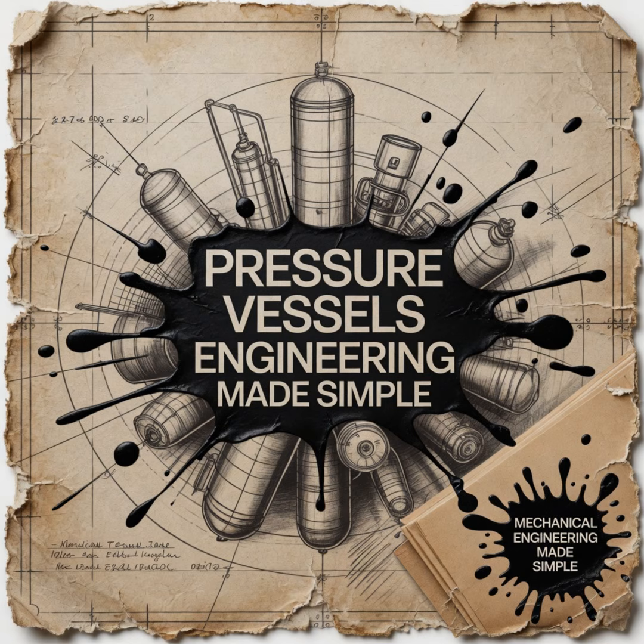That is incredibly effective for any metal. But if you are working with ferrous metals, carbon steel, which is highly magnetic, you can use an even more advanced technique, magnetic particle inspection, or MPI. How does magnetism reveal a physical crack? MPI is fascinating because it doesn't just find cracks on the surface, it can find cracks buried a few millimeters below the surface. The inspector uses heavy electromagnetic yokes to induce a massive magnetic field directly across the weld joint.